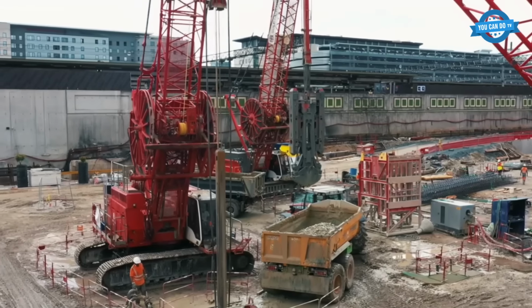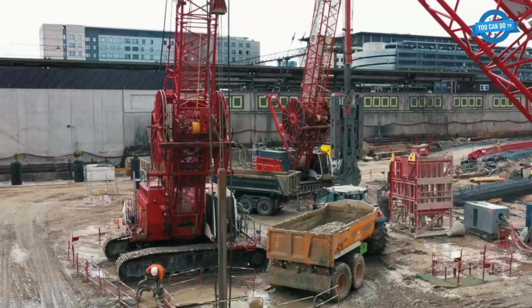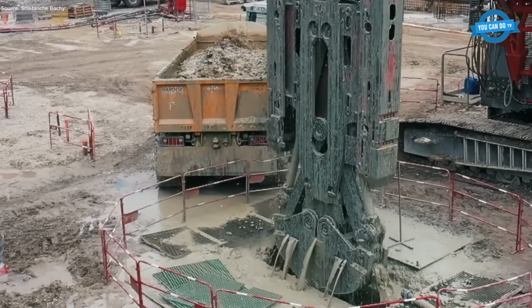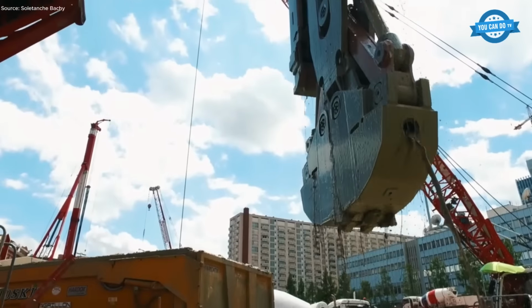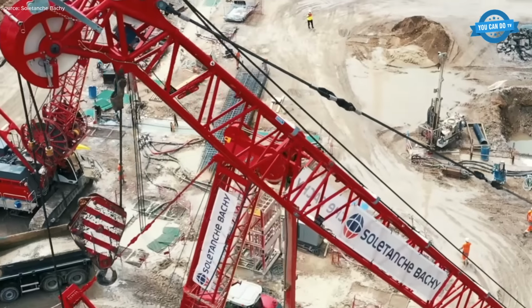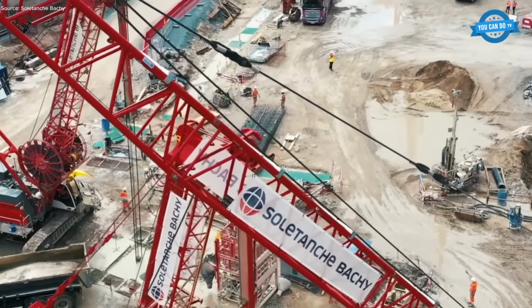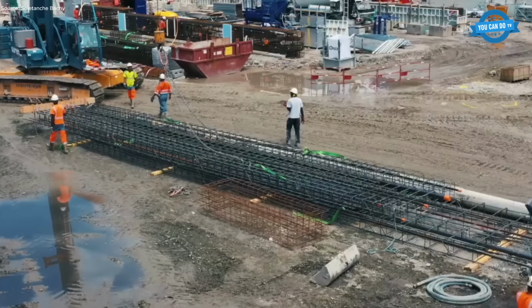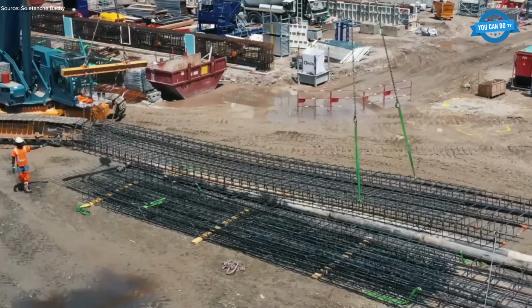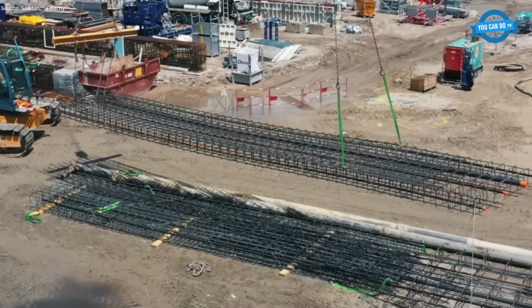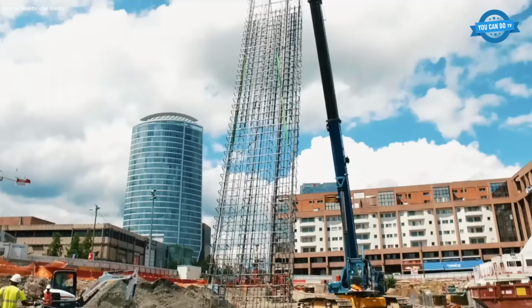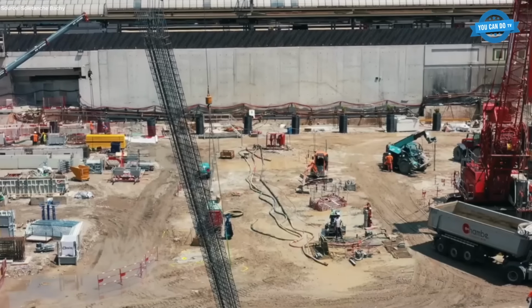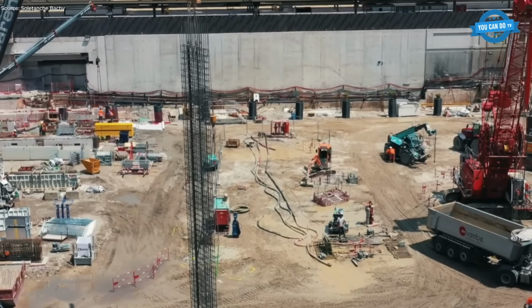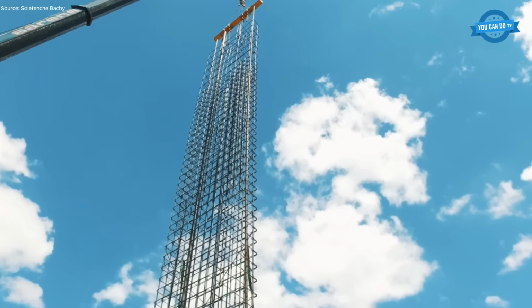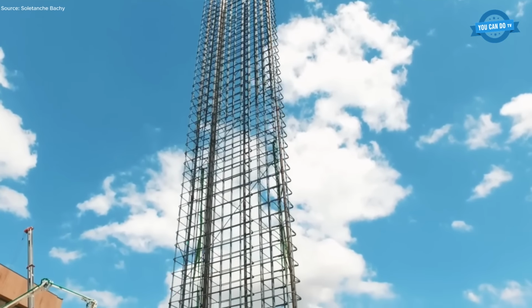For the parking basin excavation, diaphragm walls and barrette foundations were constructed to stabilize deep excavation zones and support the surrounding infrastructure. Approximately 18,000 cubic meters of reinforced concrete were placed during these structural works. Ground stabilization was further reinforced through pressure grouting operations, combined with the installation of about 1,000 micropiles, reaching depths of roughly 35 meters, ensuring adequate load transfer and settlement control in challenging soil conditions.